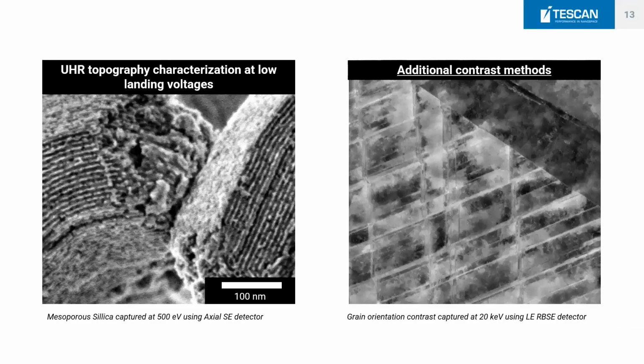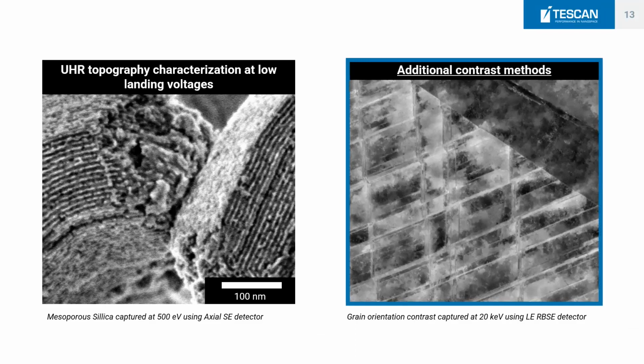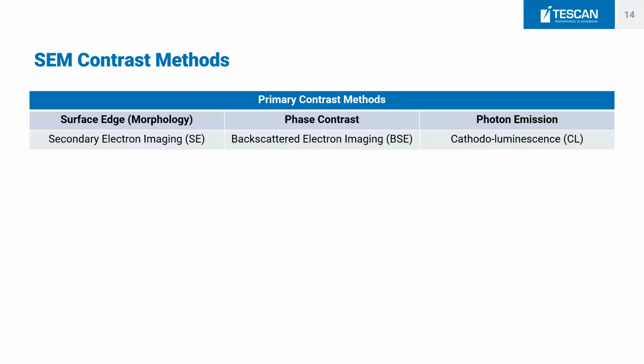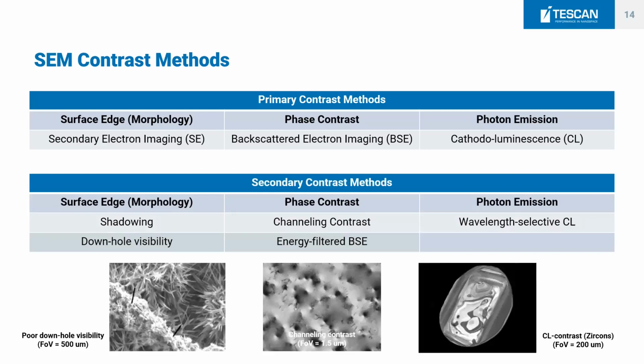But there are not just these images, which you could see on the left-hand side, which is topography, but there are also those which have importance when it comes to additional contrast methods. So I just want to mention that there are primary contrast methods. You have surface, which is the secondary electron imaging. You can describe phases with backscattered electron imaging, or you can describe photon emission. So for example, in mineralogy, when you want to see zonations of the grains, you use the CL. Those are three primary contrast methods, but you have also secondary contrast methods. So you can basically divide each of these contrast methods into its secondary contrast methods counterpart.